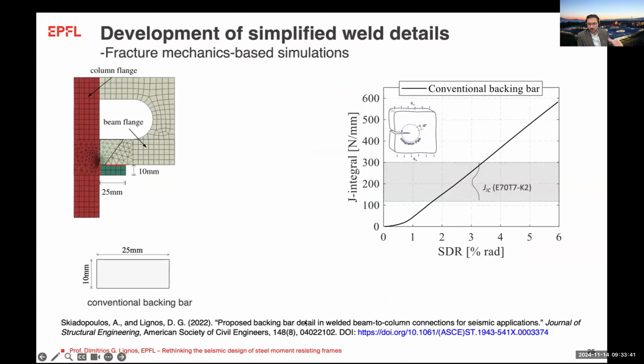And obviously, such an endeavor requires testing, but before you do tests, it's also good to do simulations. Here we used conventional fracture mechanics-based simulations, where we looked at what would happen in the joint if the conventional backing bar remains in place. In this diagram, you see that for a pre-Northridge connection, when your J integral, which is a conventional fracture mechanics metric, matches what you get from the weld, at around 1.5% drift, assuming the variability on the weld electrode, you would get more or less fracture if you leave the backing bar in place.